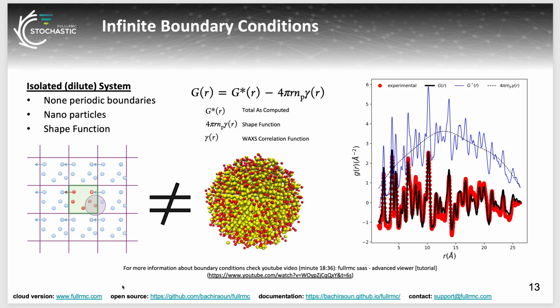The way we do that in general is we measure a system in solution, then we measure the solution by itself, and we subtract the two signals, and we end up in an artificial kind of experiment where we isolate the nanoparticles, for example, in solution. And if the solution is dilute enough, it's going to look as if we are measuring isolated systems.